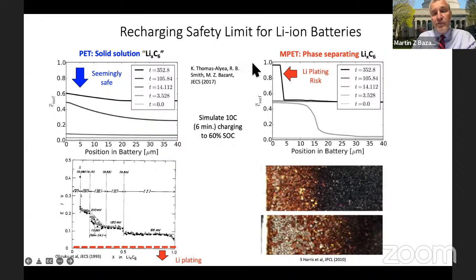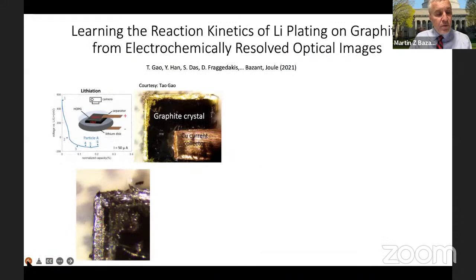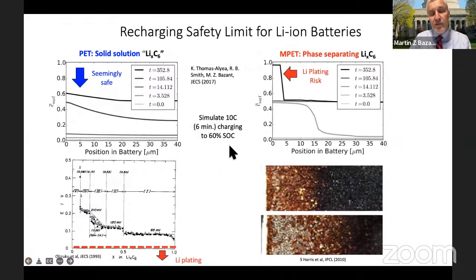And in fact, if you switch to our model, then when you do that same simulation of fast charging, you find that when you get to 60%, most of the particles are sitting at 50%, but near the separator, a bunch of particles had jumped to 100%, and those are the ones that are high risk of lithium plating. So what we showed in this paper is really, for the first time, why you cannot charge your batteries faster.